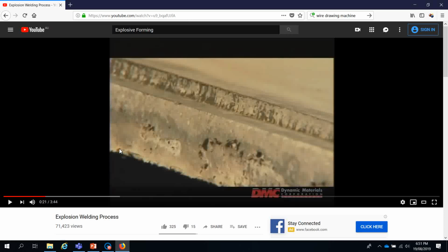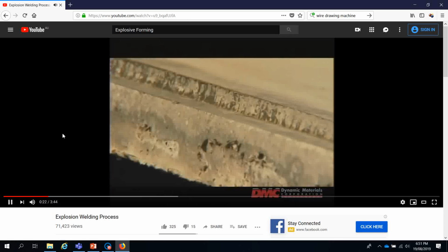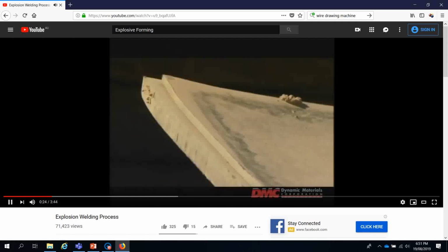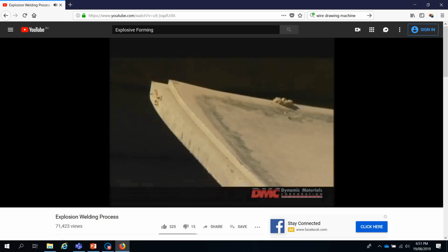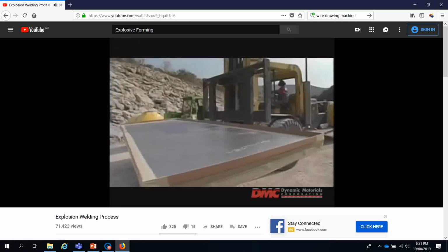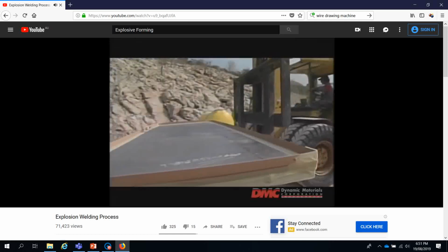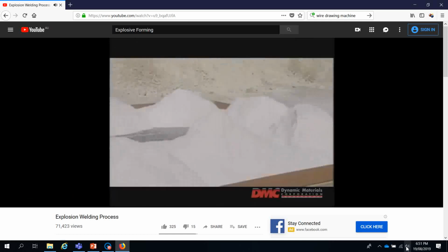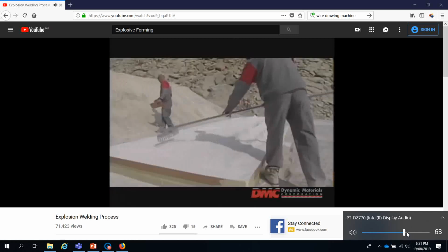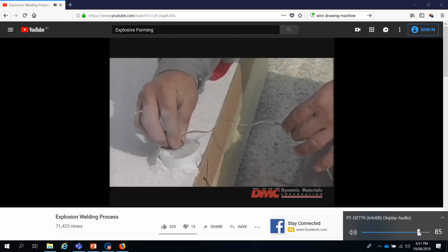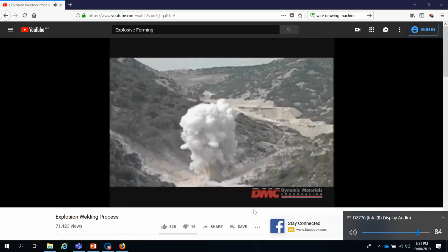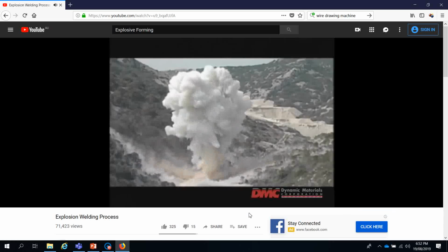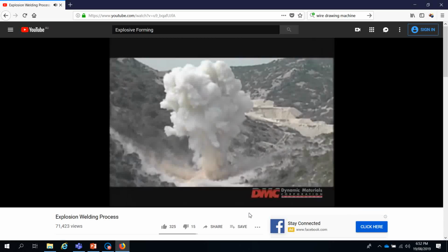The explosion welding process begins as soon as two metal plates arrive at DMC's production facilities. To maximize the welding force of the explosion, the surfaces of each plate are ground as uniformly flat as possible, a process that also removes any rust, oxides, and other surface flaws. They are then ready to be assembled into a pack, which locks the plates into position for the explosion. To build a pack, the stronger and thicker of the two plates is laid face up.